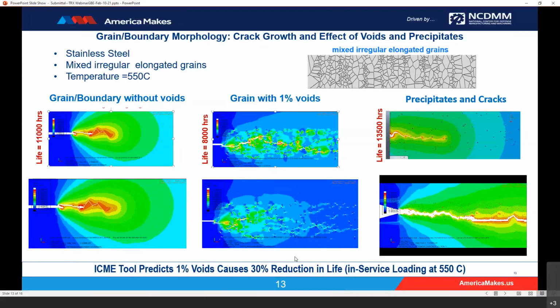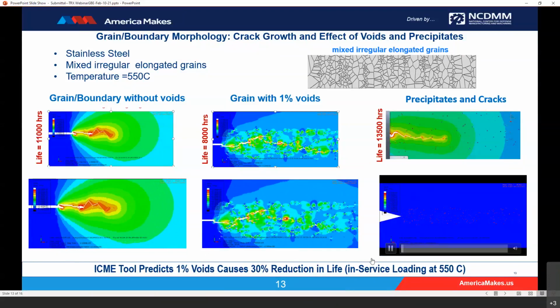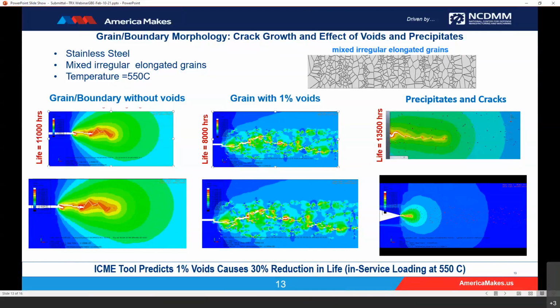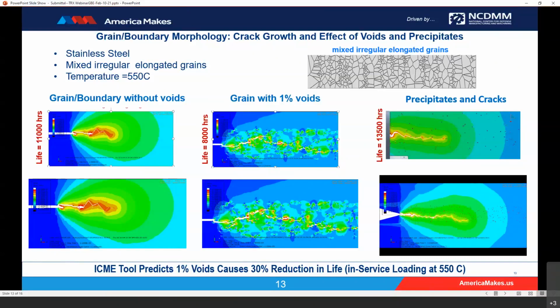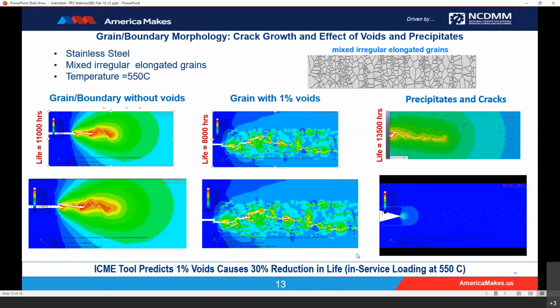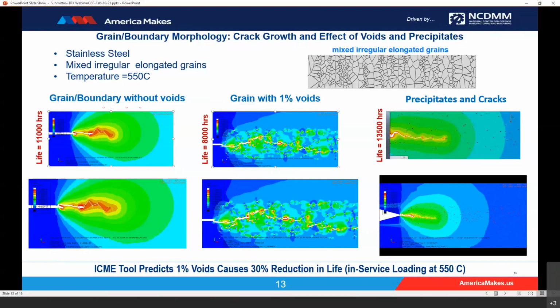Now, with the incorporation of precipitates, which you can see slowly as red dots on the right-hand side, the precipitates act to control the crack propagation such that the life is extended to 13,500 hours. Again, careful understanding of the voids, careful utilization of precipitates and inclusions can extend useful life. ICME tools predict 1% voids, which cause the 30% reduction in life, and in the same manner, ICME tools can predict the consequence of utilization of precipitates and inclusions to extend that life.